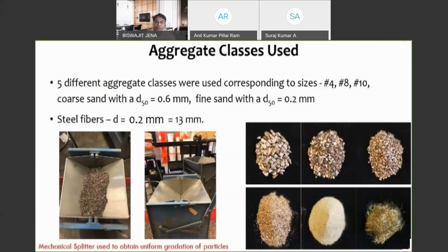We also use 2 different sands: a coarse sand with a median size of 0.6 mm and a fine sand with a median size of 0.2 mm. And we have also used steel fibers, with a diameter of 0.2 mm and 13 mm long. So we separated all these aggregates into different sizes, because you really have to pack them well, and then you use what are called compressible packing models.